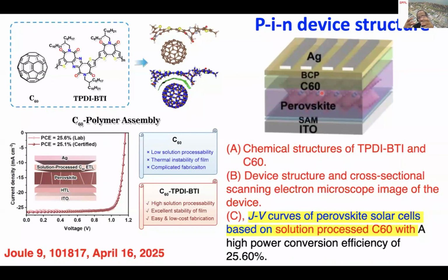But with this sublimation technique, when you use the C60, they aggregate on the surface. By aggregating on the surface, you change the energy levels. This is the drawback of the PIN configuration. So what we came up with here is we developed a material. This is some kind of organic material which dissolves the C60. By dissolving C60 into the polymer, now you don't have to sublime, you can solution process.